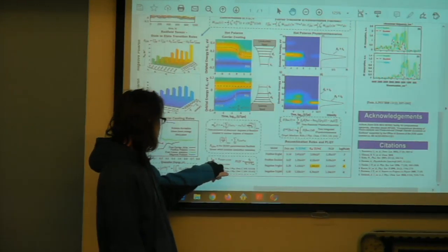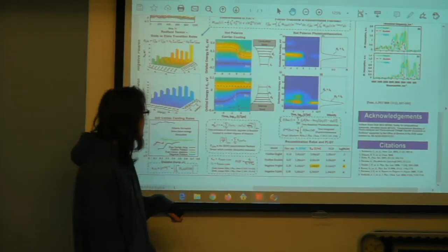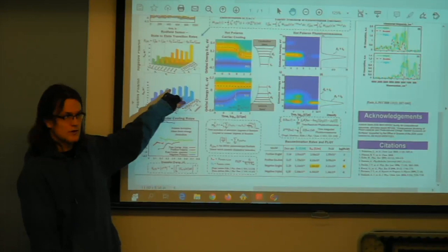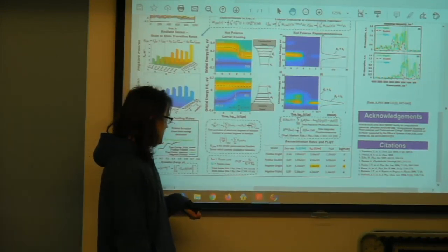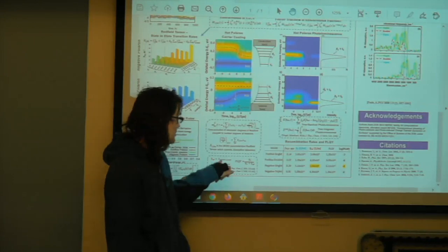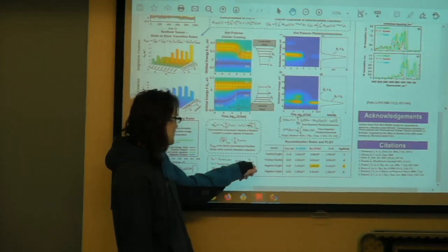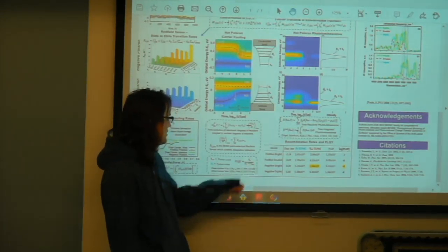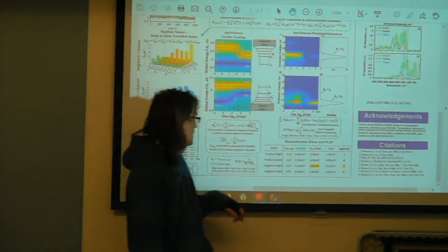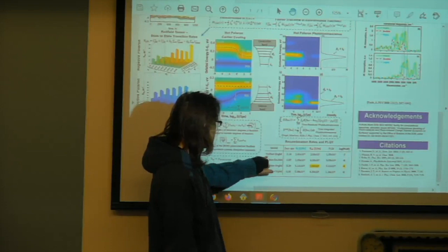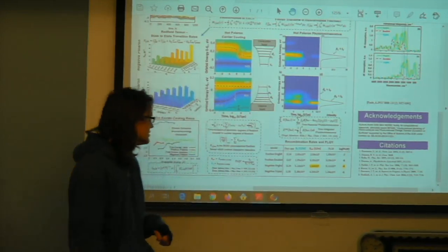We approximate the non-radiative rate from the Redfield tensor, and the radiative from Einstein coefficients. Then we can use the definition of quantum yield, the radiative over the sum of the other pathways. What we see is that generally all these systems aren't efficient emitters.